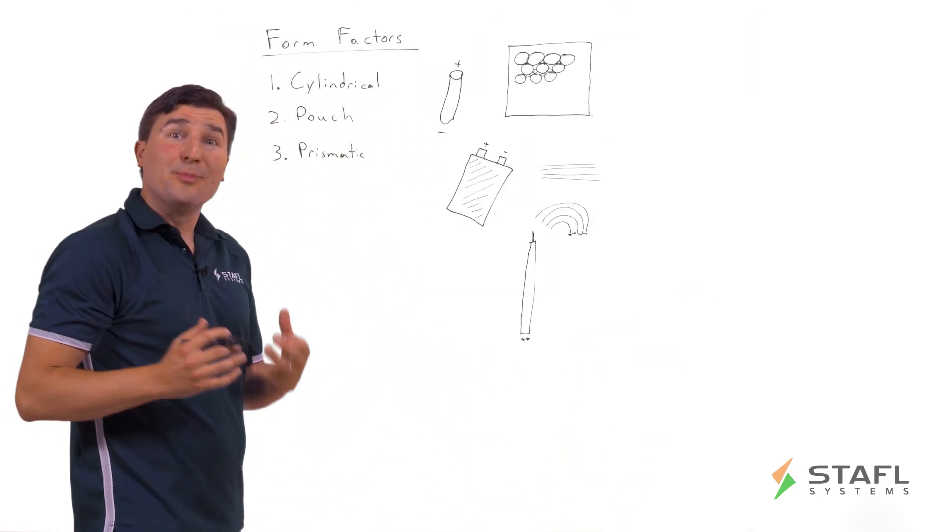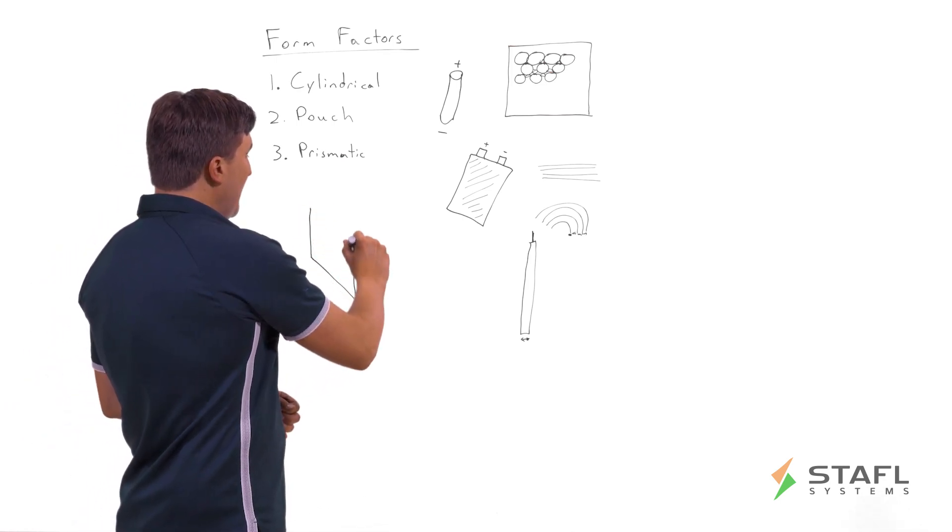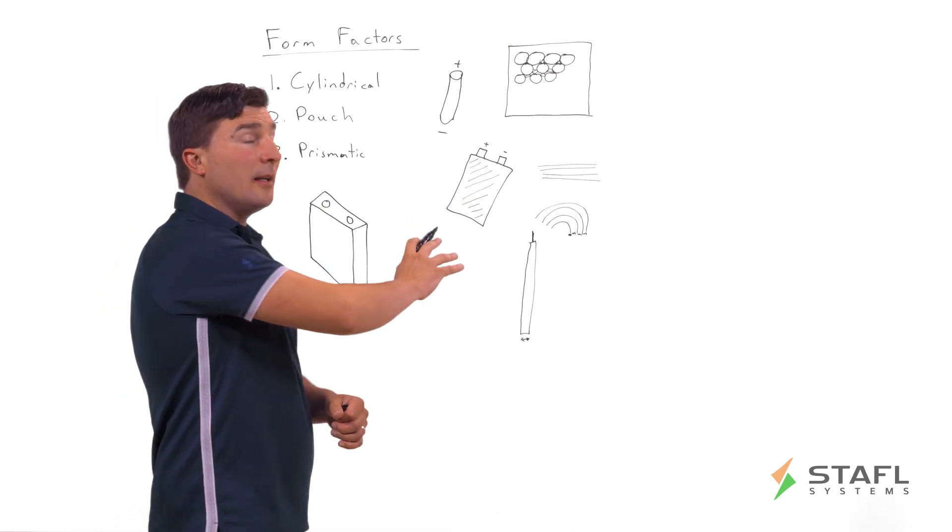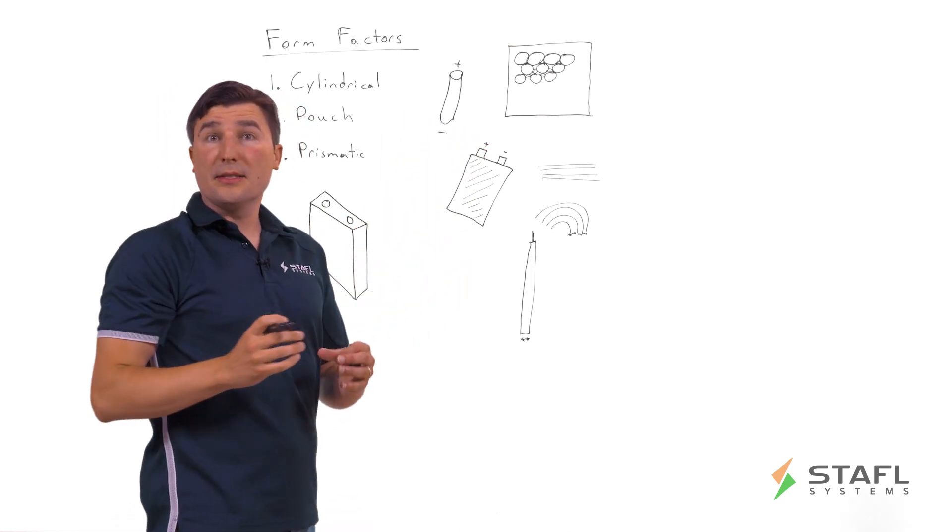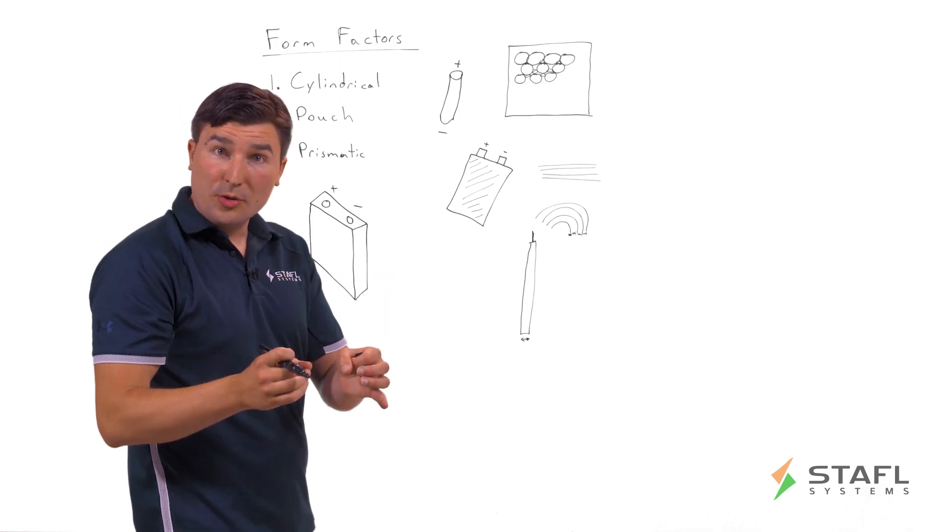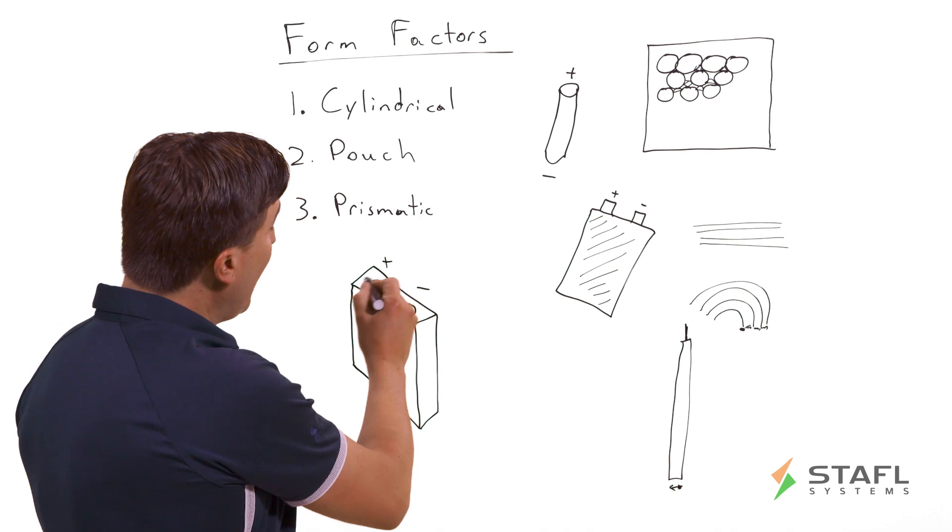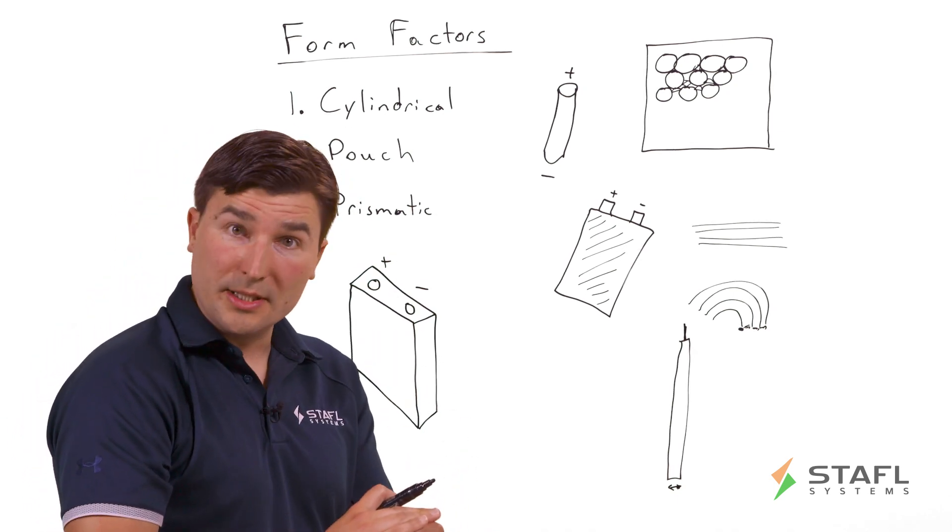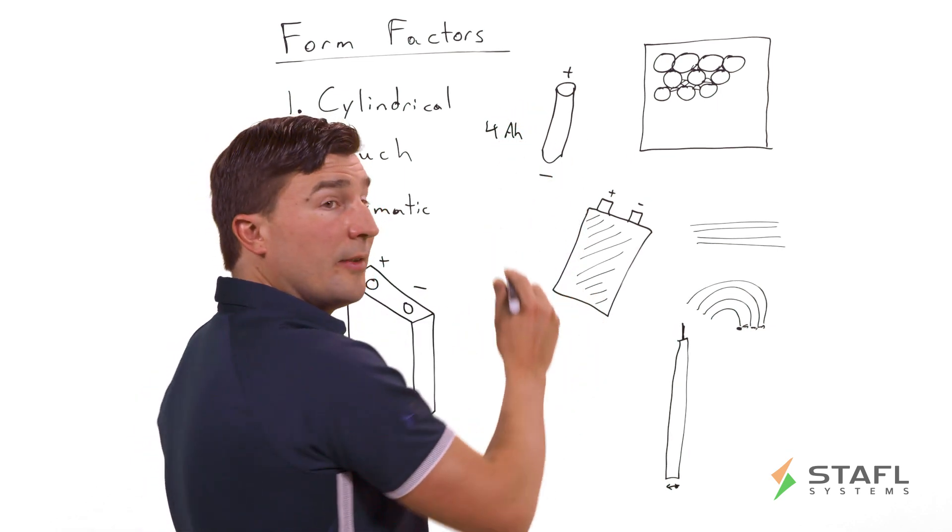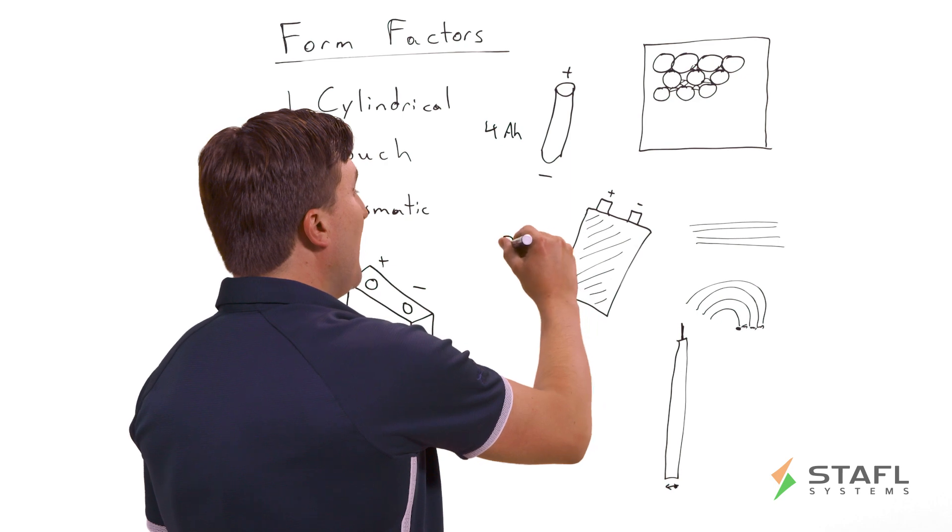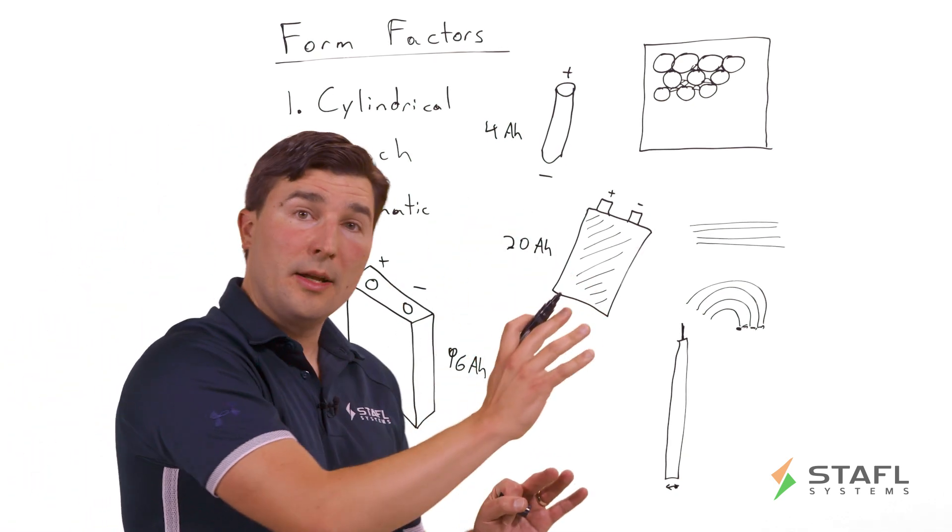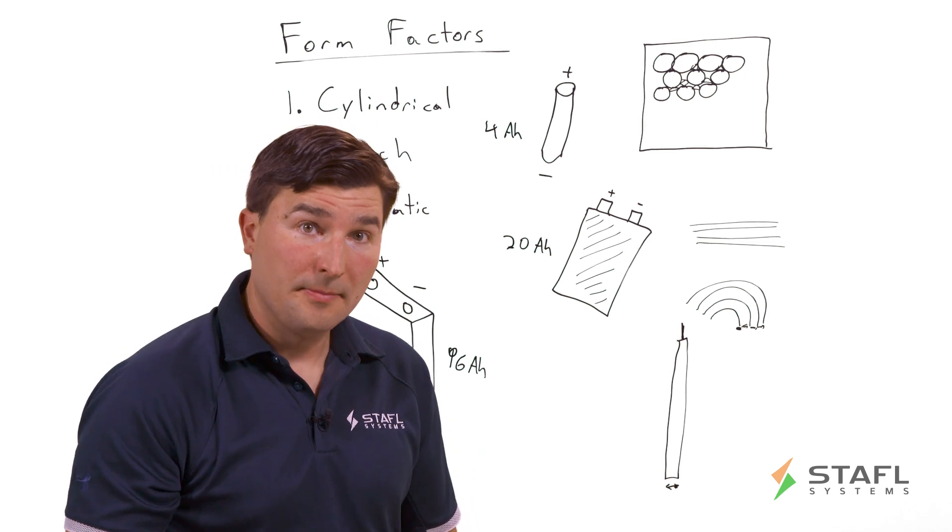And finally, let's talk about the prismatic cell. So prismatic cells are basically large brick cells that generally speaking have a much larger capacity than either cylindrical cells or the pouch cells, purely because of their larger size. So in these cells, you typically have thick terminals on the top that are either bolted joints or a laser welded tab. So you can have a very high current density connection, low resistance connection. And these cells, just for a matter of scale, whereas you might see something like a four amp hour 21700 cell, a 20 amp hour pouch cell, you might see something like a 96 amp hour prismatic cell. So that in alone in itself creates some trade-offs to consider.